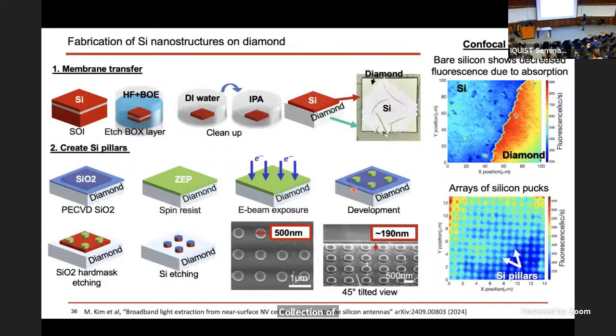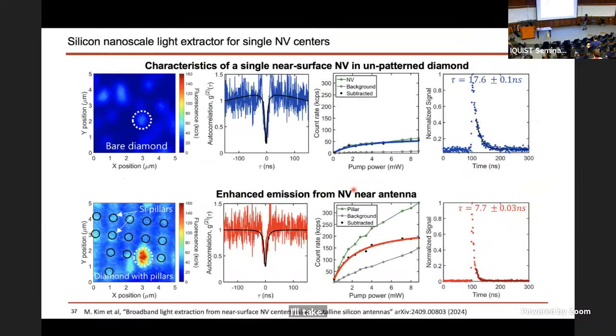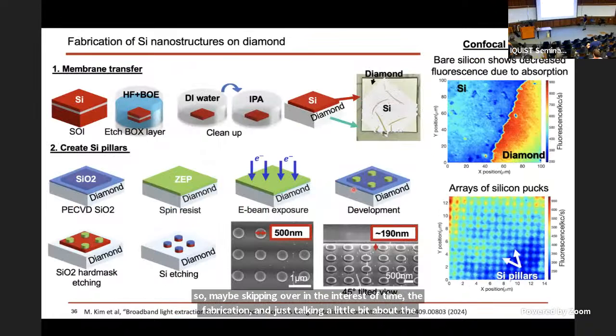And so maybe skipping over, in the interest of time, the fabrication and just talking a little bit about the results. This is a picture of the silicon pillars that we're placing on top of the diamond crystal, and within the diamond crystal are ion implanted very shallow quantum emitters. So this is what the sample looks like before this fabrication. With the absorption of silicon, you can't quite see the emitters, and then afterwards you actually see these arrays of spots that light up.